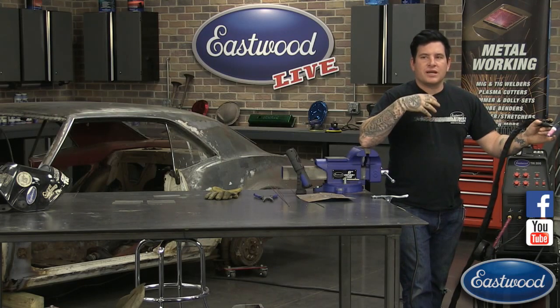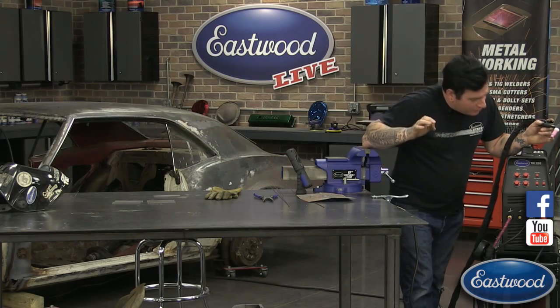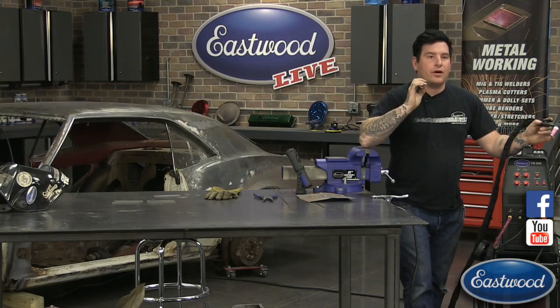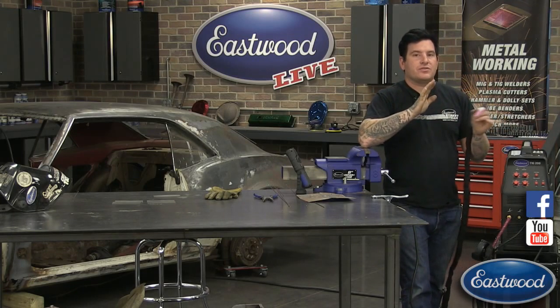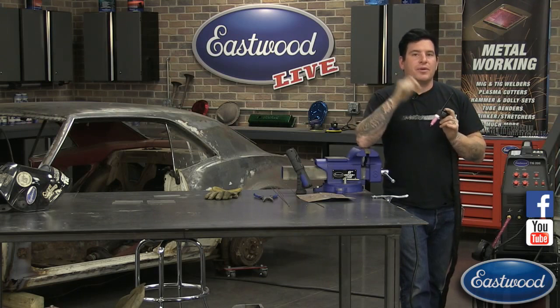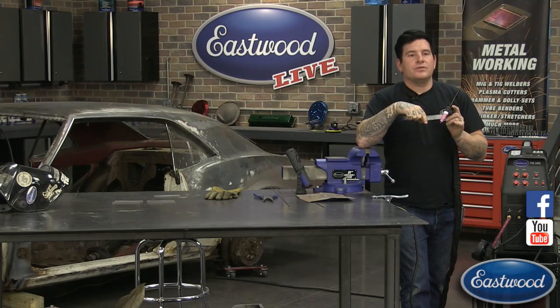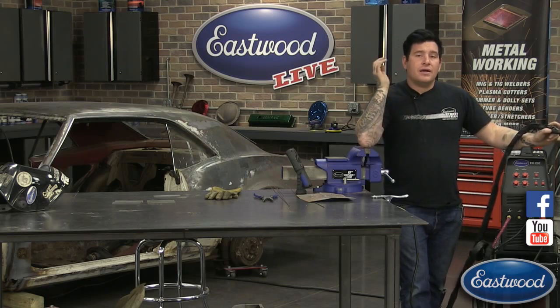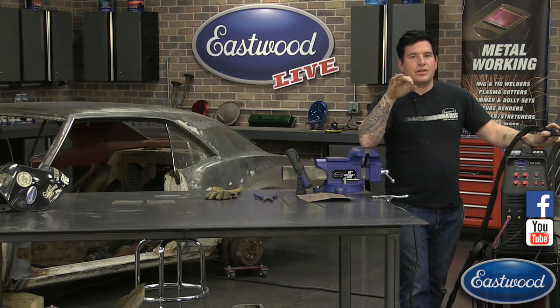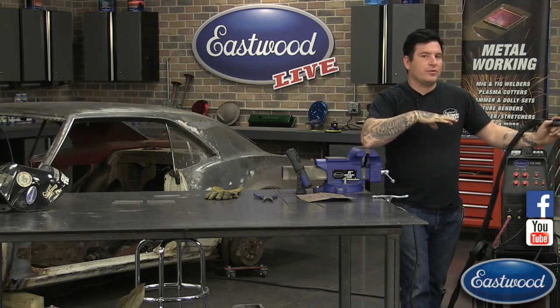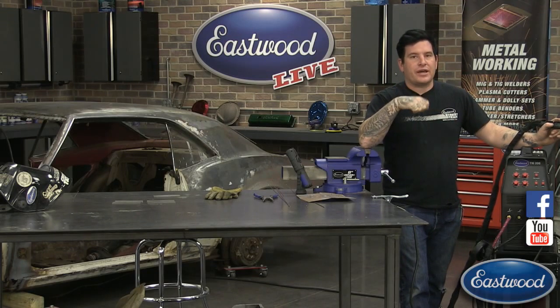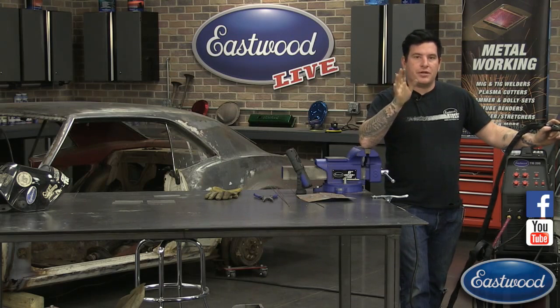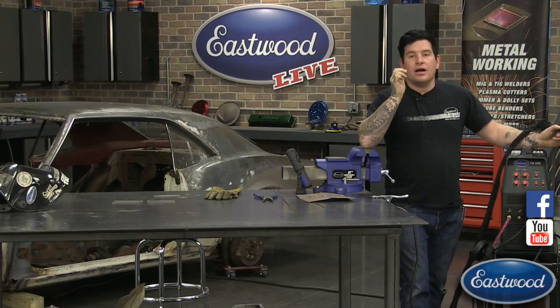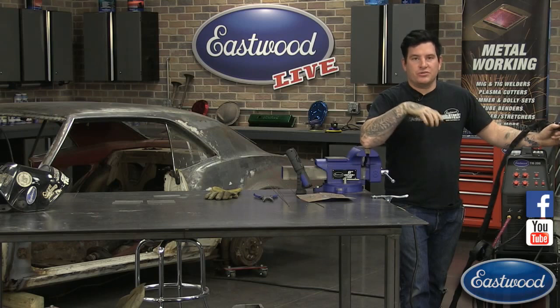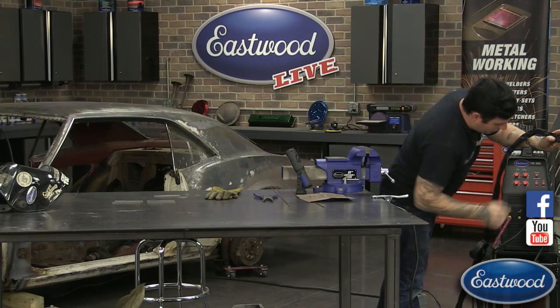On aluminum, sometimes a surefire way to see if your post flow is set too low, where you let your foot off or you pulled your hand away from the weld too quick and took the shielding gas away, you'll see a pit right in the center of the weld. I can sometimes even see a little bit of a crack. If you want to know more about aluminum, we've done a bunch of videos on that. I've done some intro to TIG welding aluminum videos that you can catch on our YouTube channel. The username is Eastwood Co. if you're watching somewhere other than YouTube right now. If you search it up, you can see that we show using this machine on aluminum, and I go a lot more in depth.